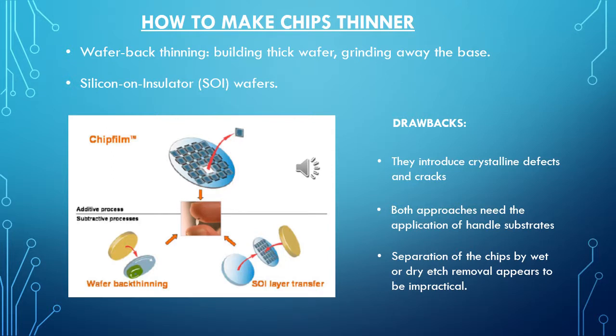But both these processes have their drawbacks. Grinding and dicing introduce crystalline defects and cracks at the edges of the wafer. Also, both approaches need handle substrates to provide mechanical stiffness and stability. The device is bonded and then debonded to these handle substrates. And the separation of these chips from the handle substrates by wet or dry etch removal appears to be impractical because of the high aspect ratio of the etching path underneath the chips.